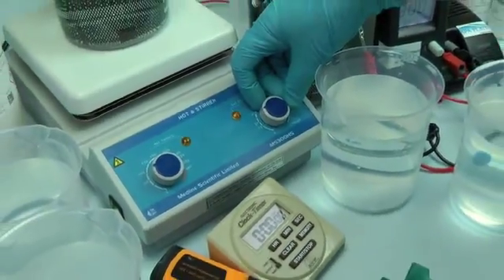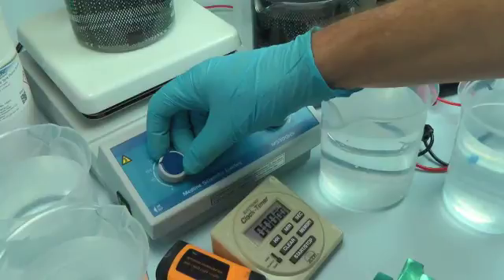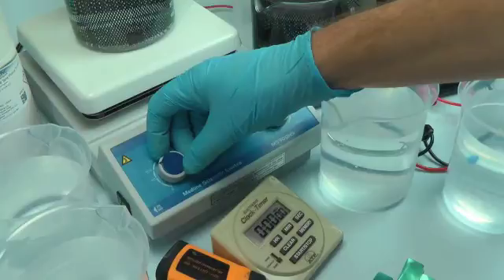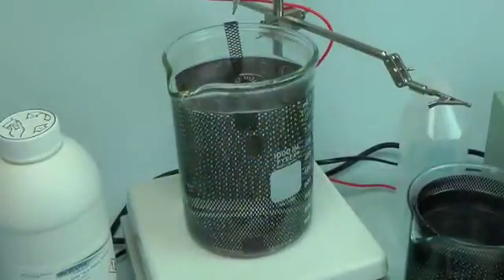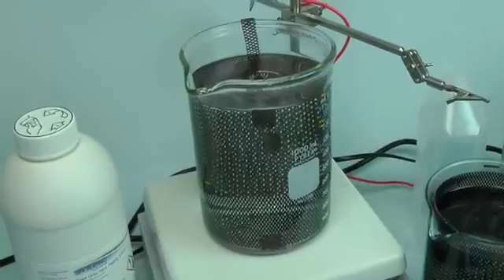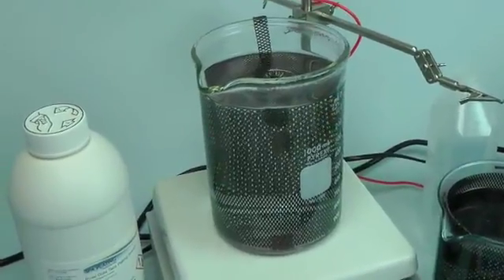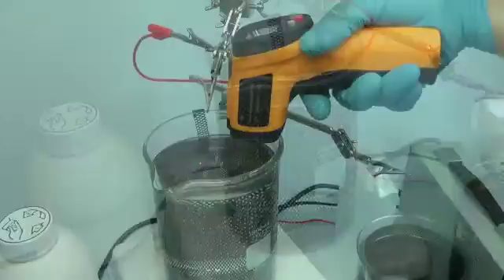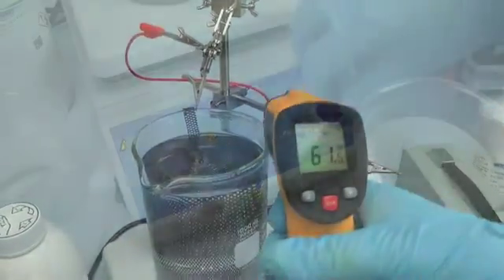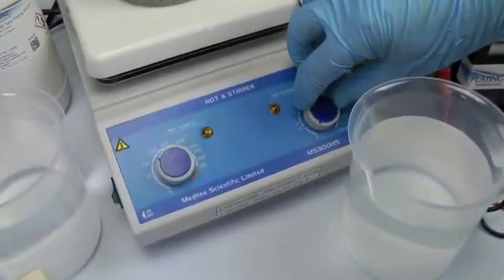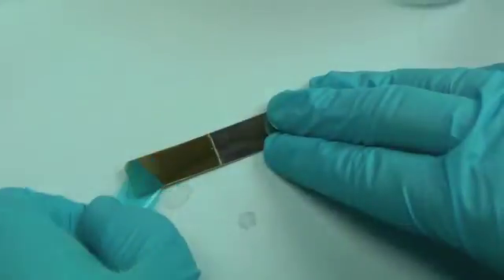Turn on the stirrer and the heat on your hot plate stirrer. Make sure you have already placed the mini stirring bar in the plating beaker, as this will help the bath reach an even temperature. Monitor the temperature with your temperature gauge, and when it reaches 60 degrees centigrade turn off the stirrer. Now you'll need to prepare the palladium plated test strip.